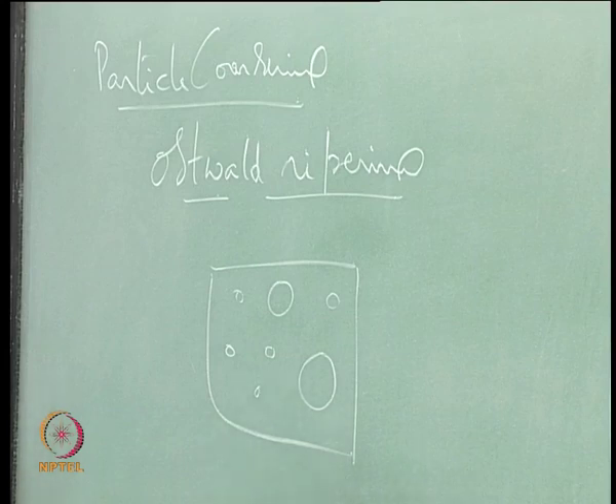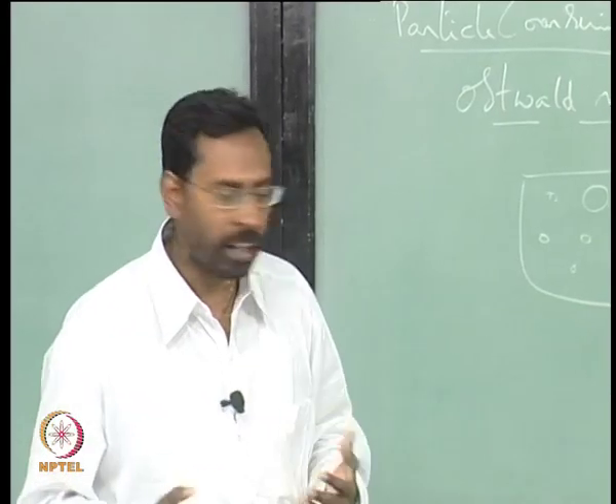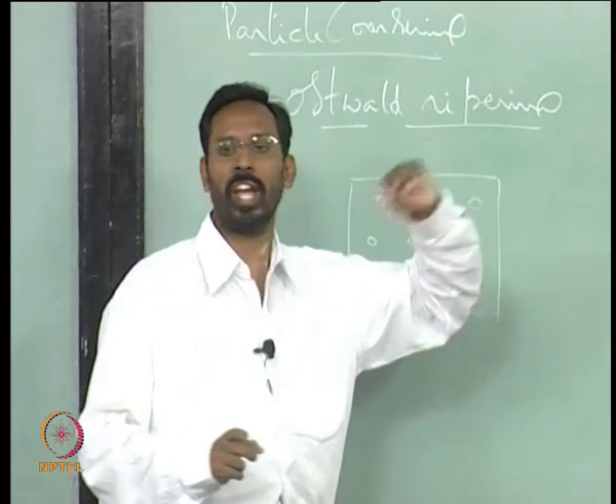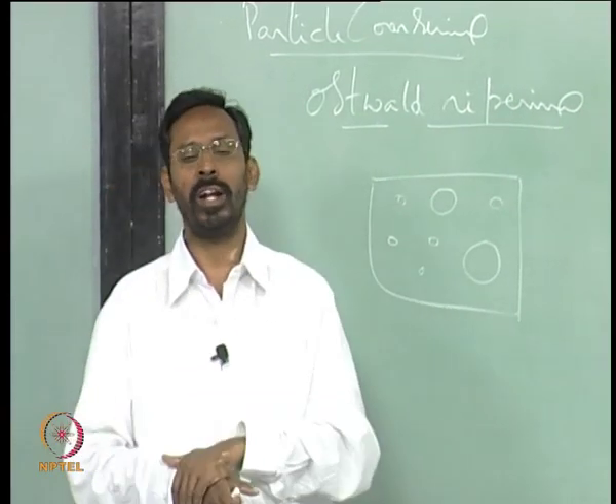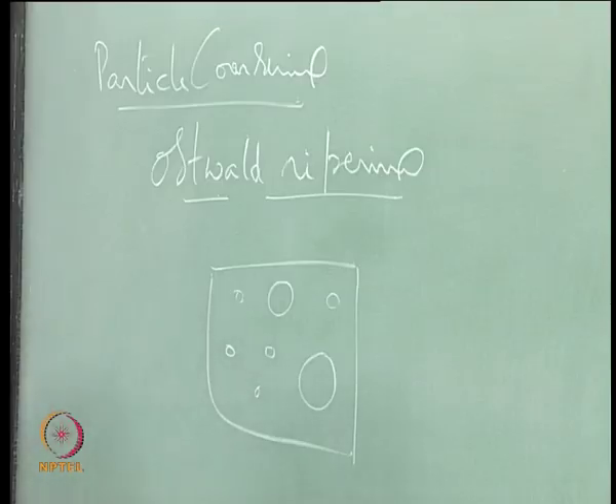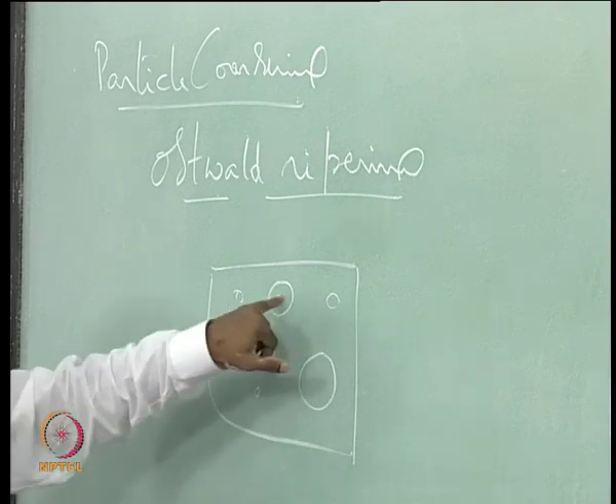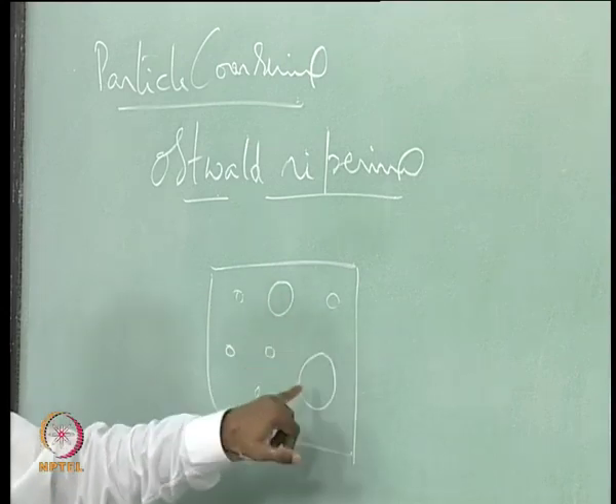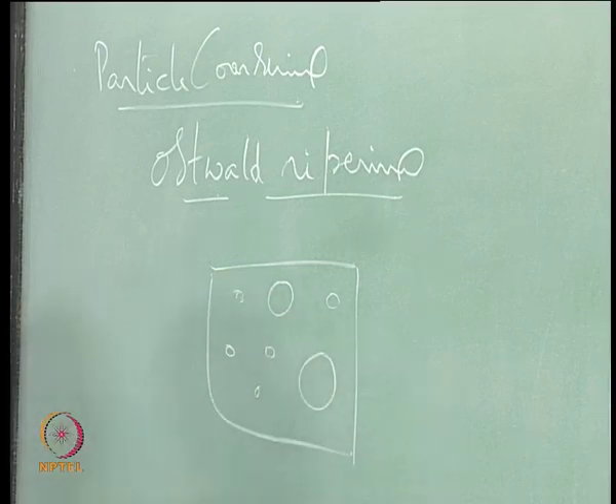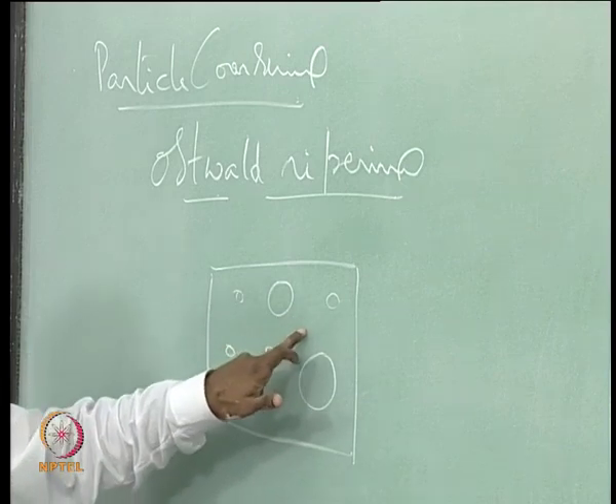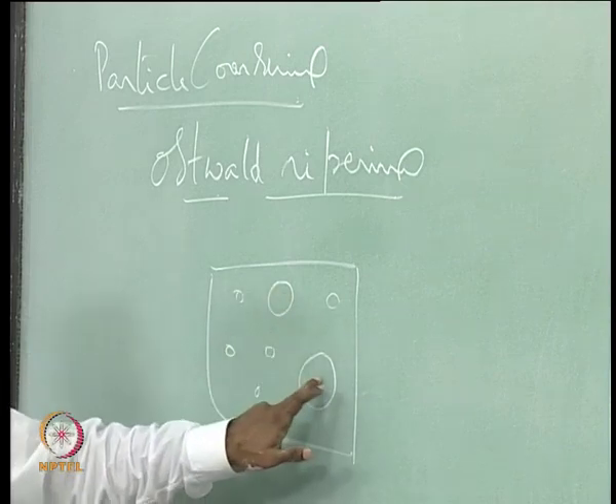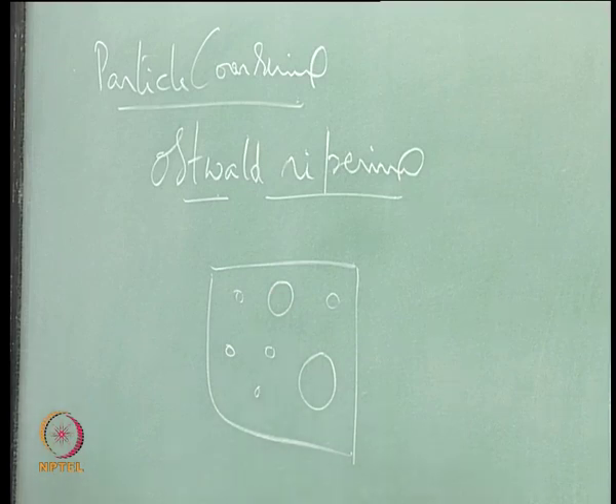We know pretty well that at high temperature you are providing sufficient thermal energy and thermal activation for the diffusion to occur. So, there is a possibility that all particles can grow, but do you see all the particles grow or not? That is where, if we try to understand this precipitate which is in equilibrium with matrix and this precipitate which is also in equilibrium with matrix, if you look at the matrix composition which is in equilibrium with this precipitate and this precipitate, it is never the same. How does it come out?